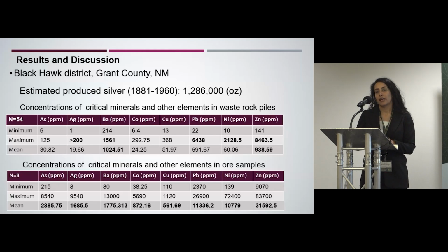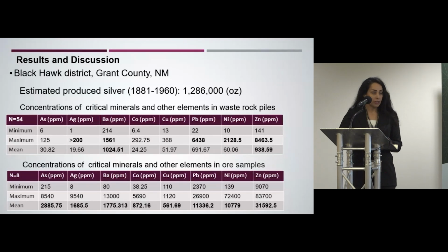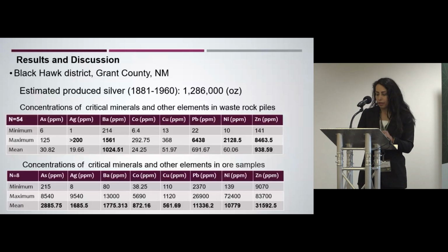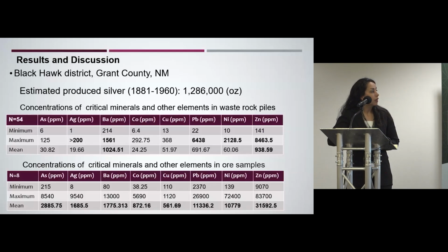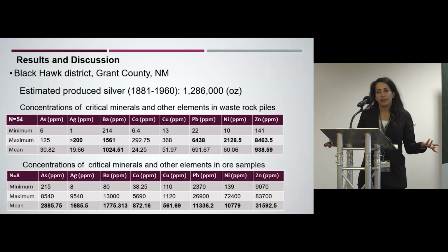Having said that, the Black Hawk samples is an arsenide five-element vein deposit that contains silver, nickel, cobalt, bismuth, and arsenic. And as you see, our ore samples are high grade in arsenic, cobalt, and nickel. And our mine waste samples are even enriched in silver. As you see, silver is not a critical mineral, but it's always a precious metal and it's always sought after. Some of our samples were elevated much more than 200 ppm in silver.